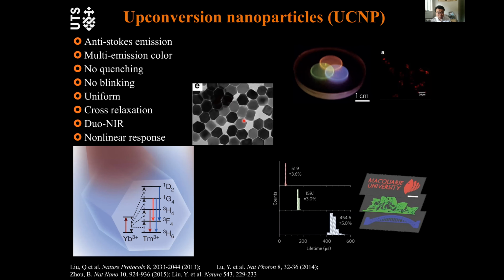So it's really good for tracking a single nanoparticle. And it's also really uniform. The size distribution and the intensity distribution of each of them are really uniform. They also have several other really good properties, like the dual near-infrared band, because the emission and the excitation can both be near infrared. They also have nonlinear response and cross relaxation. So these are all the properties of this nanomaterial.